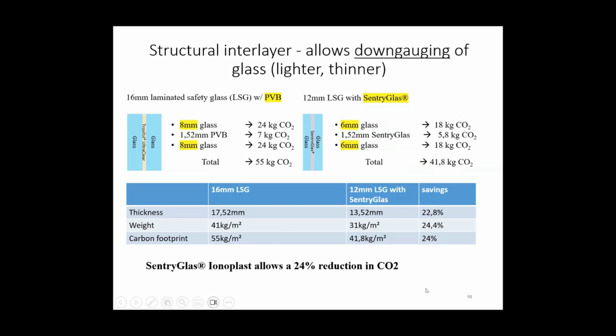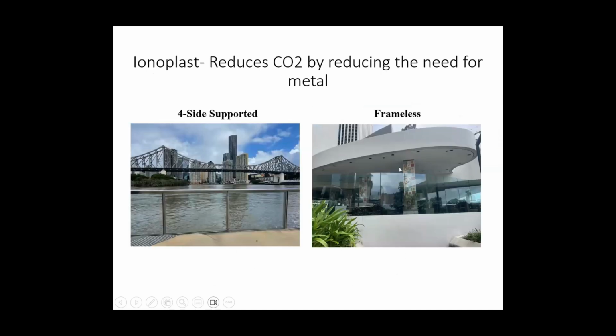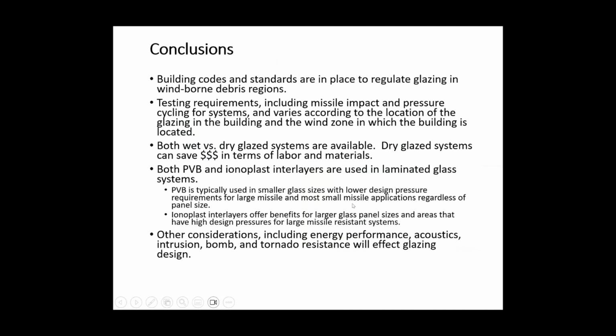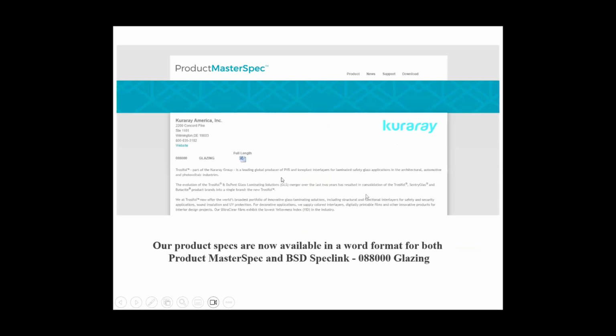And here's an example of a glass railing where switching from PVB to ionoplast, you're able to reduce the carbon footprint by 24%. And I mentioned with structural glass, you can get by with less framing. The picture on the left is a captured glass railing with metal. And in the picture on the right, there's no framing. It's only supported in the base. So in this case, you're using less metal. So less metal means lower carbon. All right, so at that point, I'll stop here.